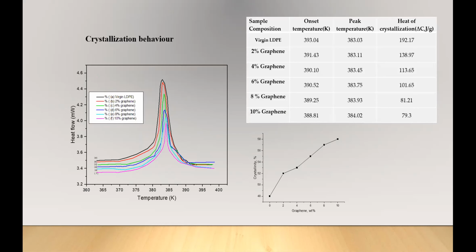Now we are coming to the crystallization behavior of the material. The DSC thermogram of virgin LDPE and its composites in the region of crystallization is recorded during the cooling scan. The crystallization behavior is over the temperature range 398 Kelvin to 363 Kelvin. The increasing concentration of graphene nanoparticles in the LDPE matrix resulted in a decrease of TCO, that is, the onset temperature of crystallization is found to be decreasing. The decreasing TCO clearly indicates the delay in nucleation.